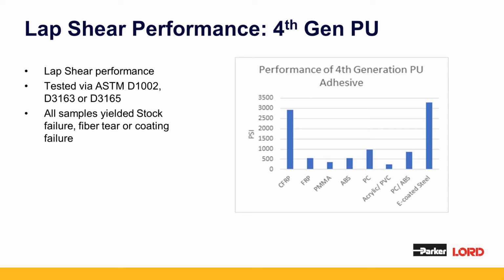So the thermoplastics such as PMMA, ABS, polycarbonate, acrylic polycarbonate ABS blend all broke during the lap shear testing. The carbon fiber, CFRP, generated much higher strength and had fiber tear, and the E-coated steel actually deformed the steel and pulled the coating, the E-coat, off the steel.